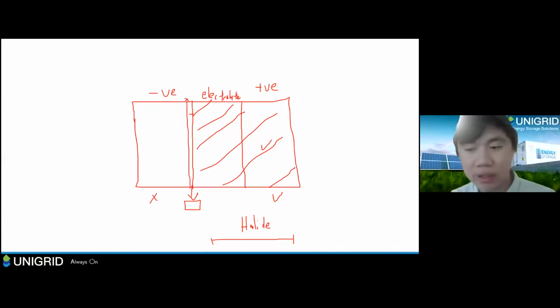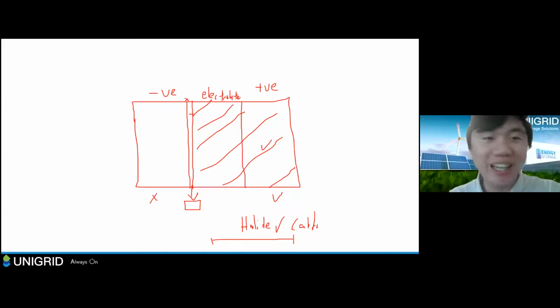Many of the high-loading electrodes today are made using a dry process, which we are currently adopting. So the region of loading areal capacity we are dealing with is about 6 to 10 milliamp hours per centimeter square, and that is simply because the sodium materials are a lot denser than lithium. So both the halide is a lot denser and also the cathode is a lot denser. So although the areal loading is higher, actually the thickness is not as large compared to the lithium. So we can do about 6 milliamp hours or higher. In fact, when we make the electrodes using a dry process, 6 is very comfortable.